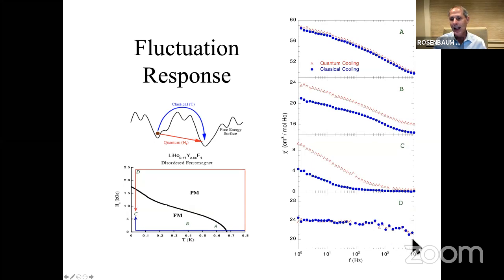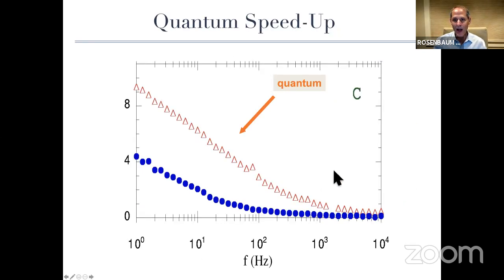We'll focus on that. And then just to convince you that there's real physics to this, if you go back into the paramagnet, there's no difference between the two, even though there's a large transverse field on. Okay. So this is the quantum speed up. What you see is that you're getting into a different physical state as characterized by the real part of the susceptibility. That was the crunching at the end of this Feynman process, if you will. You see that this lower state has a much higher susceptibility, so it's approaching the divergence. It doesn't actually diverge because there are demagnetization factors here because it's not a perfect needle. And the onset occurs at about a factor of 30 times larger in frequency than when I do this classically.